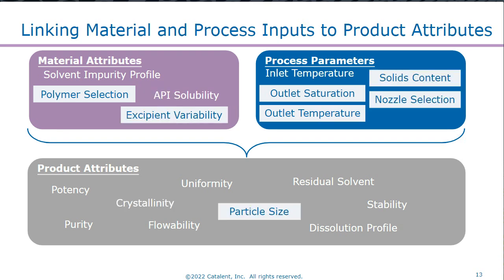Another great example is the particle size. This attribute will control things like your dissolution and your flowability. This can be impacted by polymer selection on the material attribute side and process parameters, similar drying kinetic ones, and then considerations on the solids content in that spray solution and your nozzle selection.